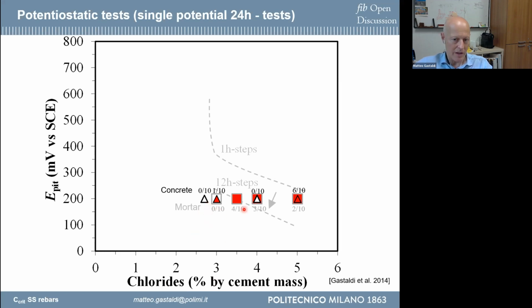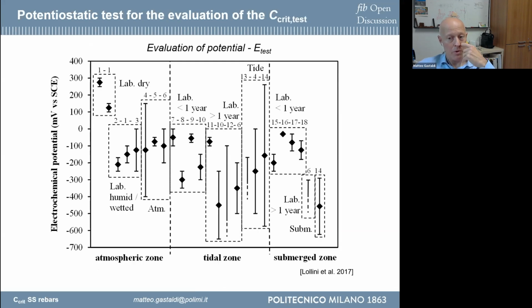And so you can obtain the statistical distribution of the chloride threshold, with no corrosion initially and then corrosion as the amount of chloride increases. If you repeat this test at different potentials, this is a static test of 24 hours, you can obtain a diagram that is below the diagram that I showed you before. And so this can give you a lower value of potential at which you have corrosion initiation. This is probably closer to what happens in tests with a very, very long time of exposure. So the problem is what potential we can consider in order to make this test, and how to evaluate it.